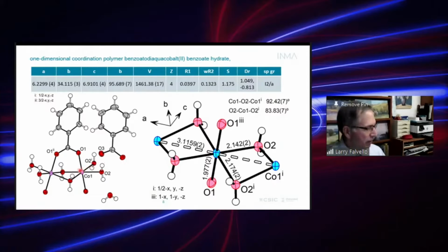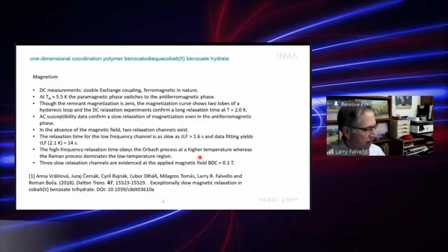It's a polymer, and the basic unit consists of 2 cobalt atoms bridged by 2 aqua ligands. There's a third bridge, which is the carboxylate fragment of the benzoate. Then, of course, to balance charge, there's another free benzoate in the structure, and there's a free water. Now, the triple bridge holds the cobalt atoms together at a fairly close distance. We'll come back to the structure shortly.